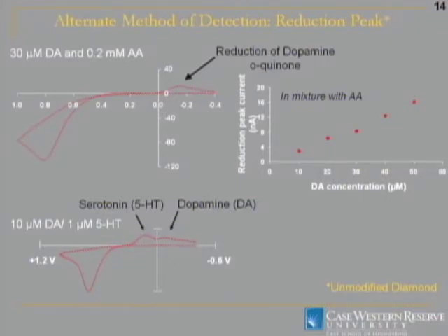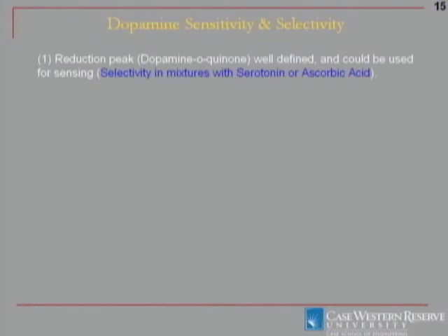Also, serotonin and dopamine oxidize at the same potential because they're very chemically similar molecules, and consequently, again, you couldn't see dopamine with serotonin present, but the reduction peaks are located at different potentials. I don't show the plot, but I do have data showing similar to ascorbic acid, where you can do a calibration of dopamine in the presence of serotonin. So that's one way we can get selectivity.